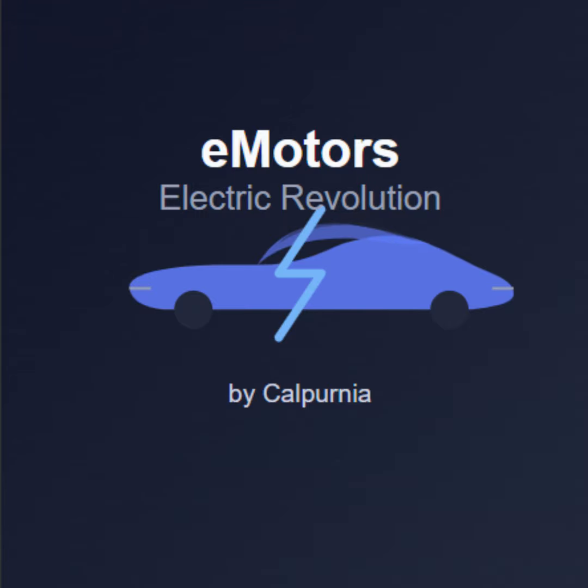Okay, and this connects directly to that common piece of advice you always hear for EV owners, right? For the typical NMC or NCM batteries, that's nickel, manganese, cobalt chemistries, which are very common. The most common in long-range EVs, yeah. The best practice for daily driving is try to keep the state of charge roughly between 20% and 80%. Don't regularly drain it way down, and don't constantly charge it right up to 100% if you don't need to. Correct. That 20 to 80 guideline is designed to minimize the voltage-induced chemical strain on the cell structure, particularly on the cathode material at high voltages and the anode at very low voltages.